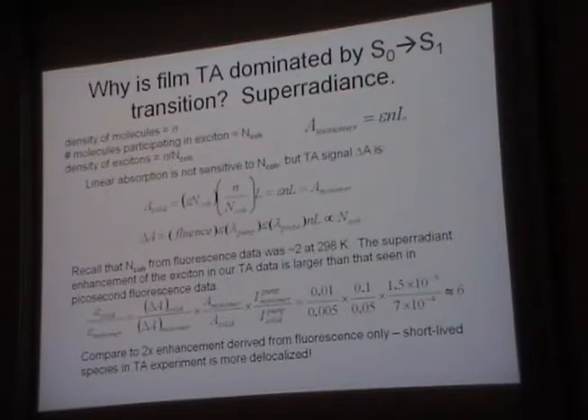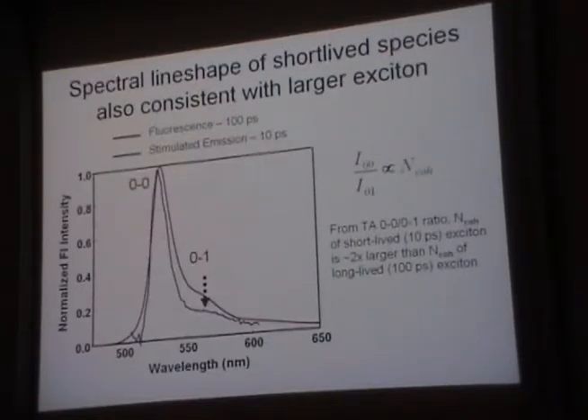That's why we have this monster S0 S1 absorption. That's why we have a big negative signal. You don't have that enhancement of the S0 S1 transition in the monomer. This is also larger than what we got from our old fluorescence measurements back in 2004. So that's a little disturbing too. Why is 6 bigger? But again, that's not the only thing we can measure. We can also try to extract the line shape of this fast decaying component, the stimulated emission that we see going away so quickly. I'm going to call it stimulated emission and justify it in the following way. You can try to pull out a vibronic spectrum of that, and what you see is it's almost all the 0,0 peak.